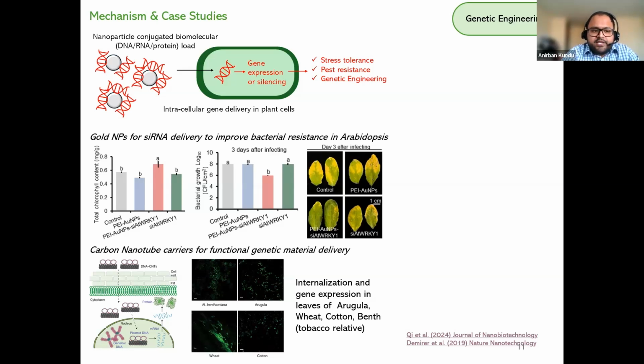So the authors have tested 4 systems. The first one is the control. The second one is only the gold nanoparticles. The third one, in orange, is the gold nanoparticles containing this siRNA. And the fourth one is just the plasmid in itself. And you see the maximum protection, or maximum efficiency, is achieved by the gold nanoparticles that contain this smaller siRNA, and that improves the bacterial resistance of Arabidopsis.